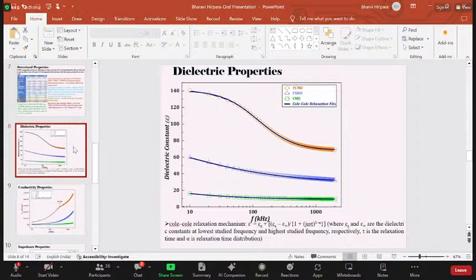And also, to understand the dipole relaxation mechanism, we have fitted the Cole-Cole relaxation model, as shown here by the equation below. From that, alpha is found to be enhanced upon doping of Sr2+, whereas it gets suppressed for the case of YCMO. A sequential reduction in tau, that is the relaxation time, is also seen, and hence the dielectric constant is understood to be enhanced from YMO to YCMO to YSMO.